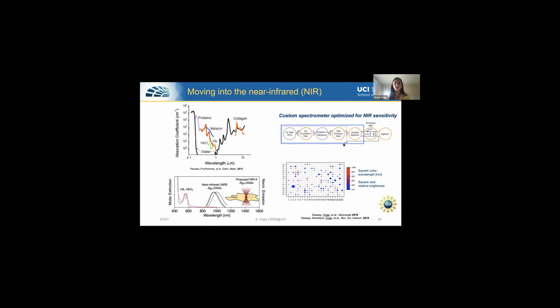So in order to do this, we designed a custom spectrometer. This was work led by my former collaborators at UC Santa Barbara, Stephen Swayze, Hunter Nicholson, and Elizabeth Gwynn. And by looking into the near infrared, even at the silver clusters that we had initially designed but couldn't see into the near infrared when we did that design, we found